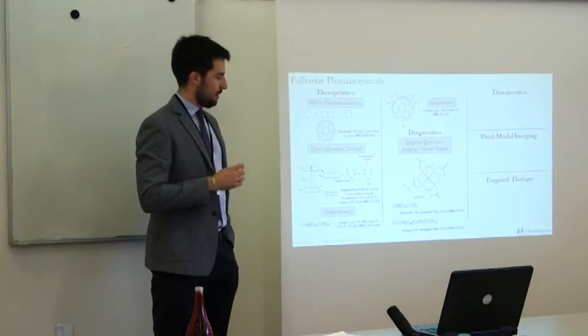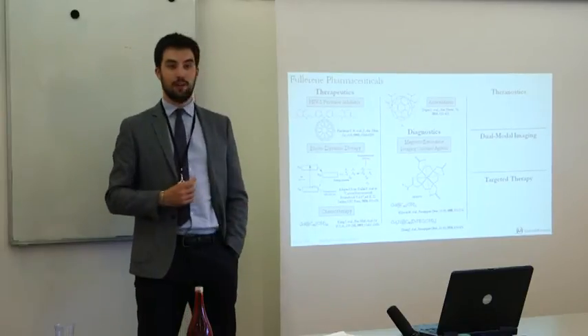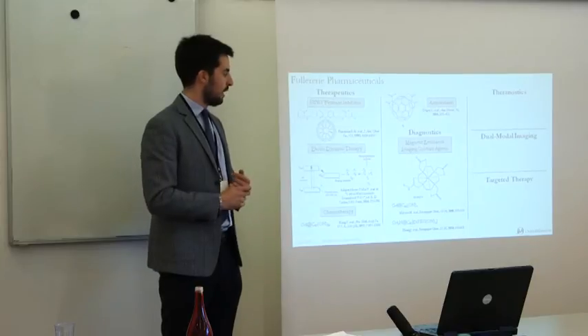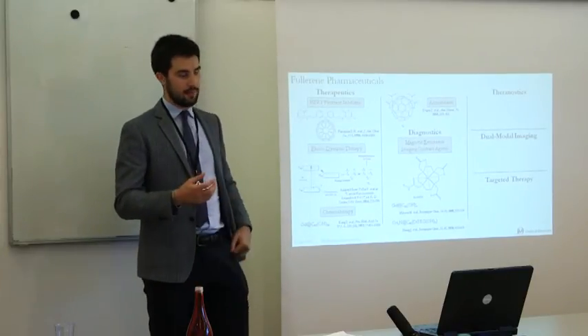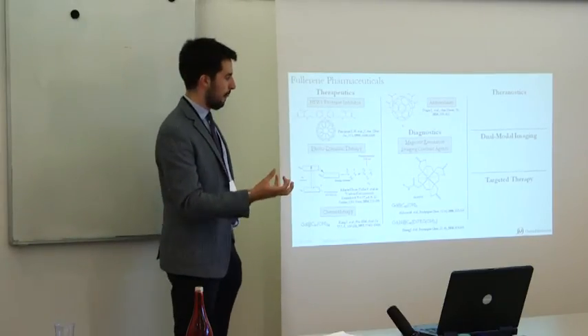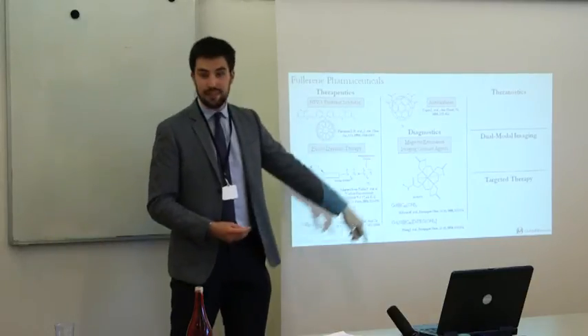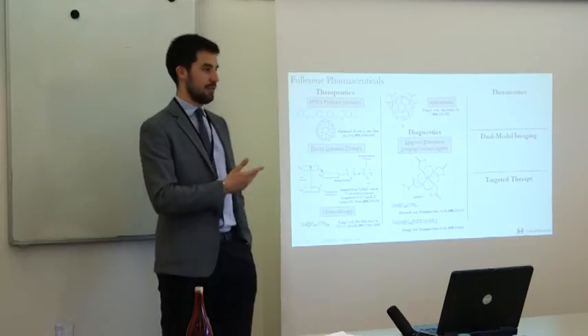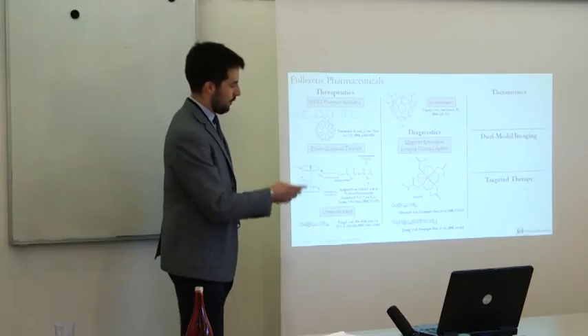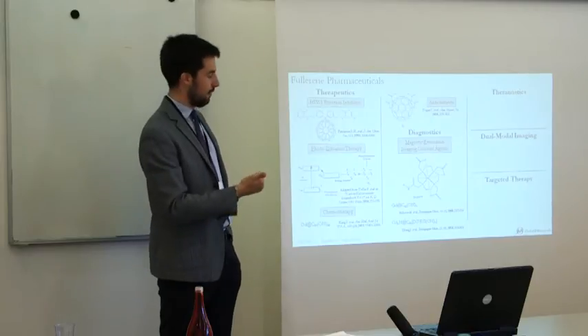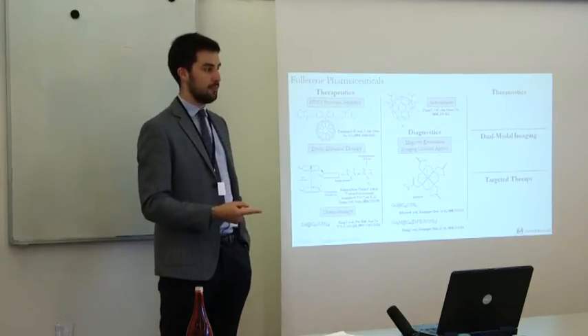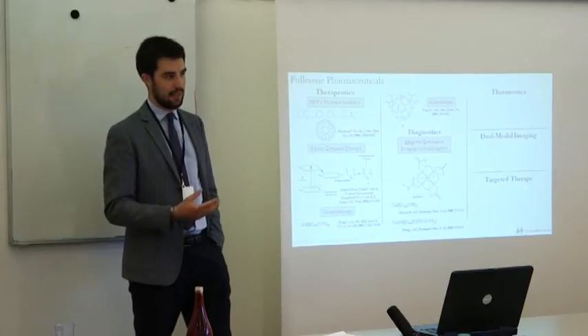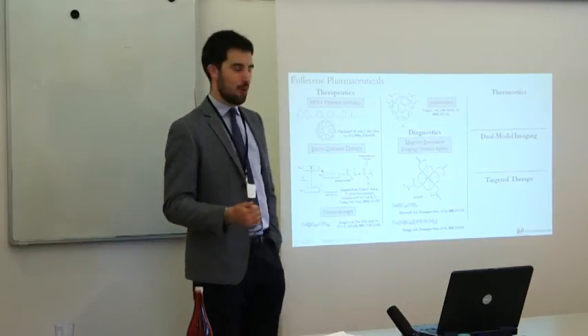On the diagnostics front, a key one which I will laud again at the end is for MRI contrast agents. If you've ever gone for an MRI scan, hopefully not, but if you have, then you're often injected with a contrast agent in order to make the picture better. That is actually just a gadolinium chelate. The gadolinium basically relaxes the water protons which surround it. It does this in this chelated state. The thing is, in this chelated state, it can actually become unbound. It can become loose. Gadolinium, if you have kidney problems, is fatal. You can't have a contrast-improved MRI scan if you have kidney problems. If you capture gadolinium inside a fullerene cage, it can never escape. That's great. The other benefit is people have water-solubilized these gadolinium fullerenes. The contrast is actually two orders of magnitude better than the agents which are currently available. This is great.